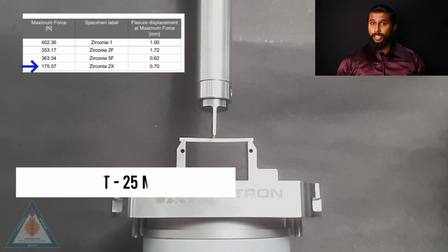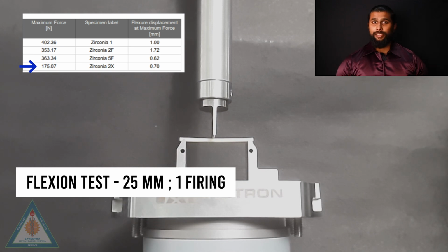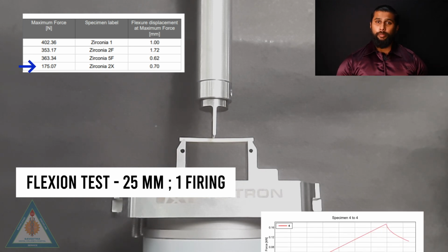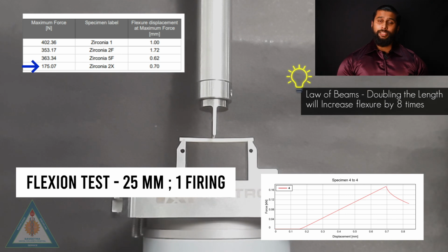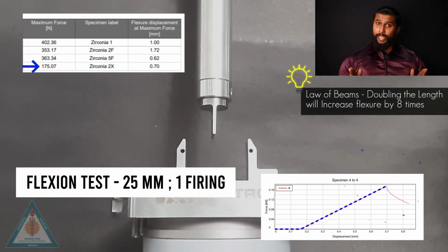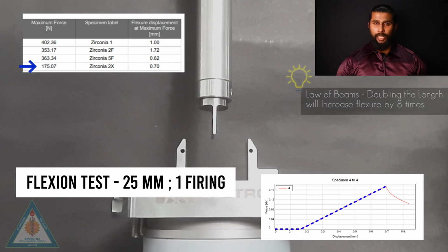Now the sample that is twice the length displays lower flexural strengths as well. And this is due to something known as the law of beams, which states that a sample that is twice the length flexes 8 times as much compared to a sample that is half the length. Now this clearly demonstrates why a long span, unsupported, small framework is a very poor choice for zirconia as a restorative material. Now despite all this, how does zirconia manage to be as amazing as it is?